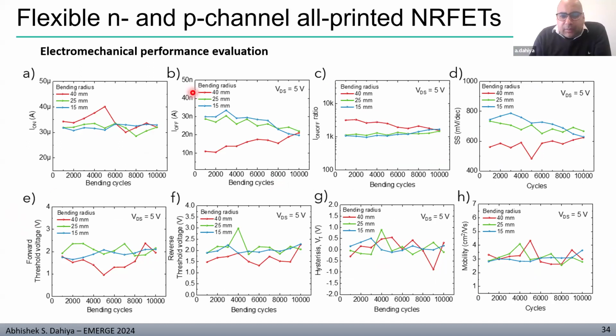And in this case, we reached up to a bending radius of 15 millimeter, which is again not as much as some who have done around 5 millimeter. But the device performance varies, though not so significantly that it cannot be compensated through circuit design. So the initial tests, I would say, look robust for this approach. But yes, encapsulation techniques such as optimized plasma to have good adhesion, then encapsulation, which can bring the active layers into the neutral plane, where it is experiencing less strain. These are the approaches I think we should take, and that can improve the robustness of these devices.